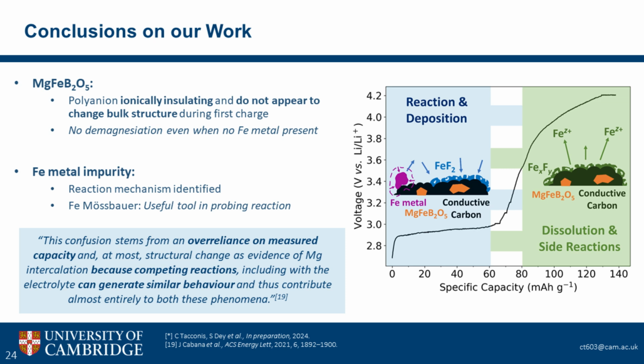And what we notice as well is that there's no proof of demagnesiation even when the iron metal is not present. So really recently I've been able to finally synthesize this material, which is quite finicky to make, without this iron metal impurity. And you really don't see the demagnesiation. So it isn't the fact that we've got this going on that's stopping our material from demagnesiating. And then what we've seen is tracking with this iron metal impurity, we've identified a possible reaction mechanism.